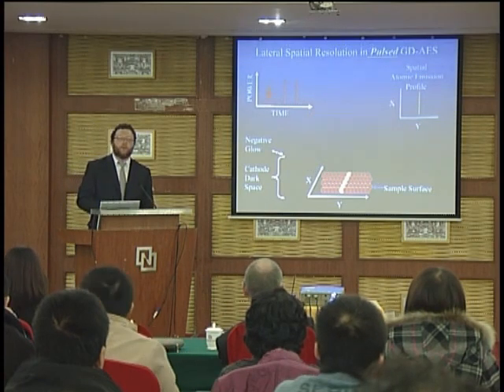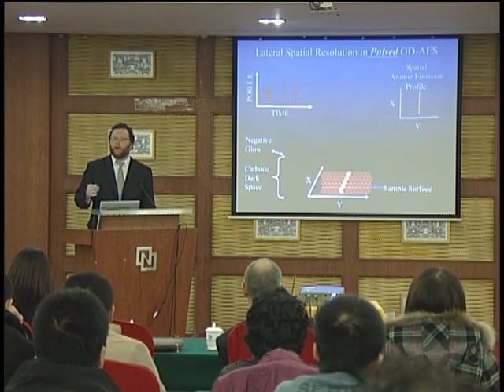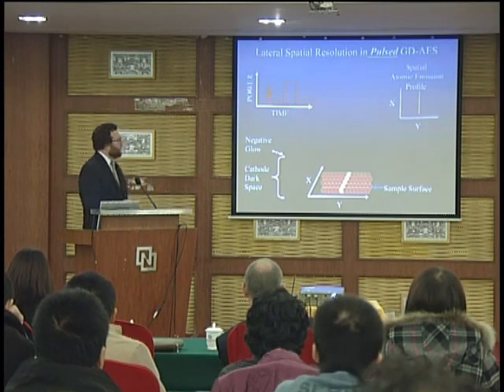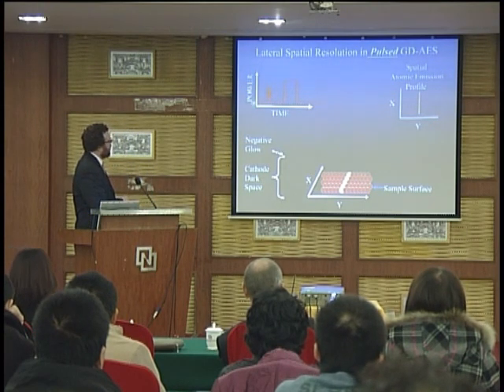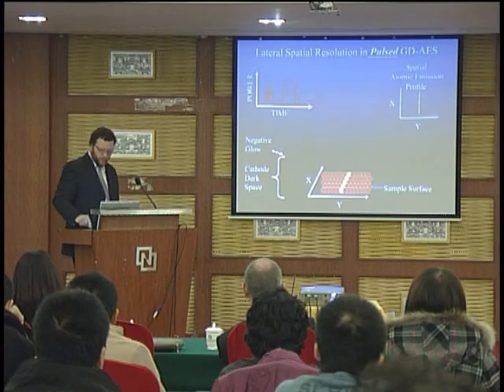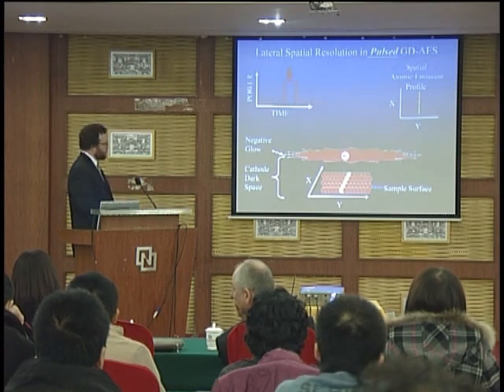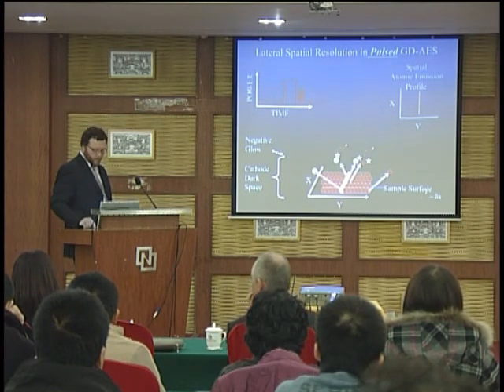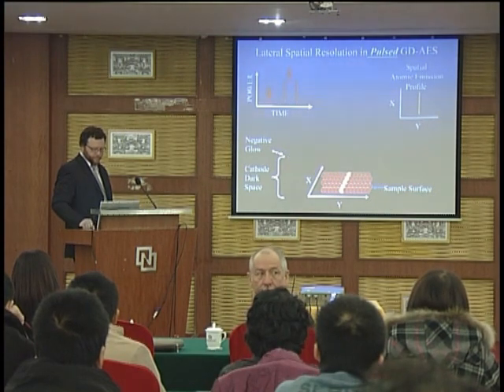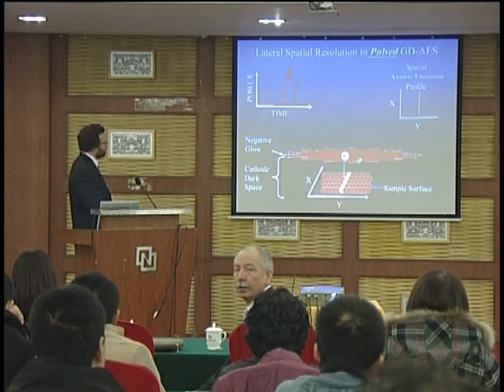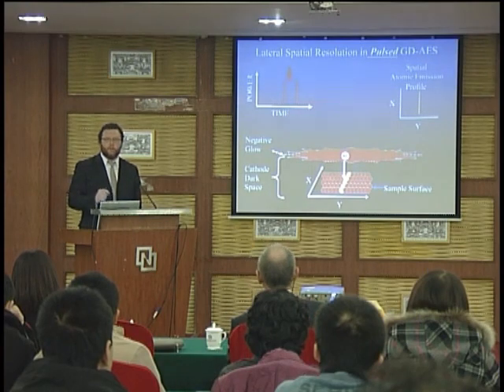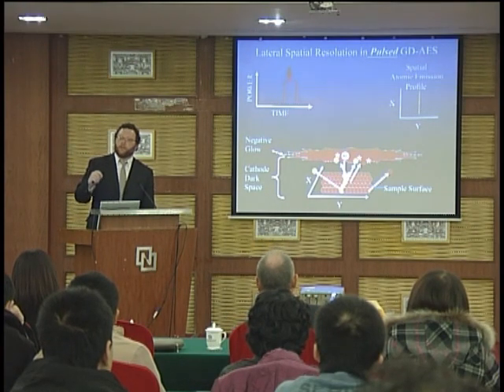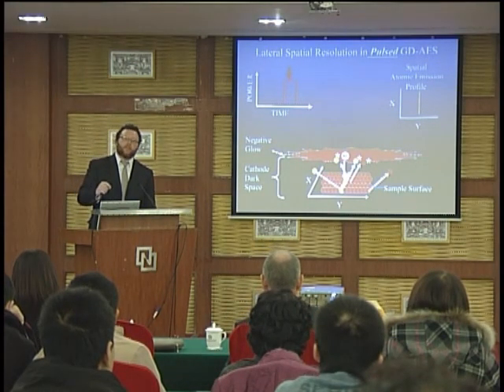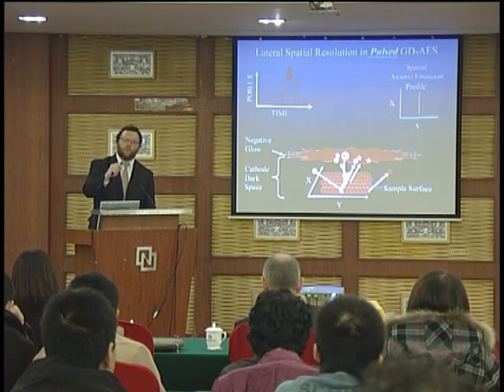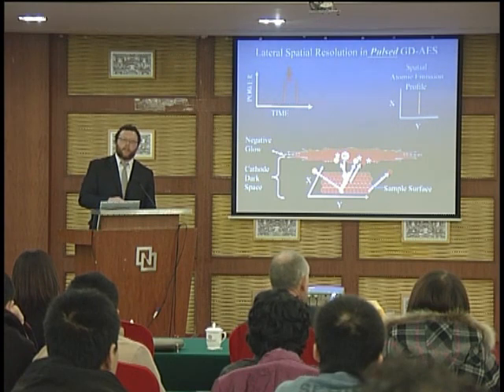But if you were to think about doing this with a pulsed glow discharge, you can solve the problem pretty simply. Now we have a pulse power waveform, so typically it's off, and then we turn it on, the glow discharge forms, and immediately we start to sputter away material from the surface here in the same way that we did before. But now, because the plasma has a short lifetime, that means that there's not a large distance that the atom can move from its origin into the negative glow before it's finally excited and emits.